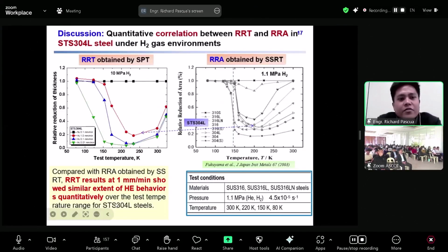And if we compare our results, RRT, obtained by our SPT, to RRA obtained by SSRT from other research groups, it showed a similar extent of hydrogen embrittlement behavior in different temperature range applications. Particularly when we compare our results at 1.0 millimeter per minute punch velocity by SPT. Therefore, we conclude that our simple testing method is reliable in screening the hydrogen embrittlement behaviors of stainless steel at different temperature conditions under high pressure hydrogen environment.